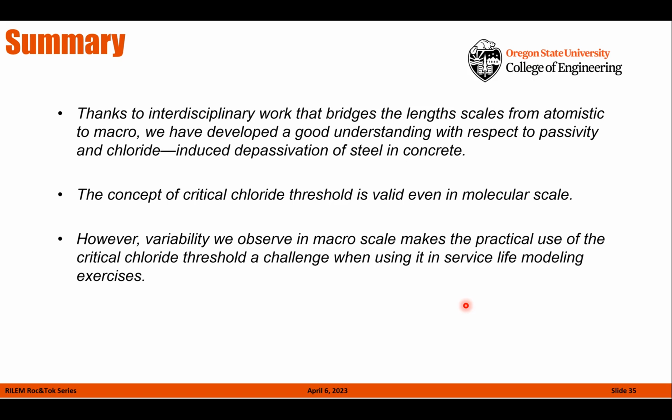We also showed that the concept of critical chloride threshold is valid, even at the molecular scale. So there's no question in our minds that this is valid. However, there's also this practical aspect that the variability we observe in macro scale makes the practical use of the chloride threshold concept a challenge when using it specifically for service life modeling exercises. And I'm going to highlight this very carefully. Chloride threshold concept is a valid concept, but with respect to using it for service life modeling purposes, there are some challenges.